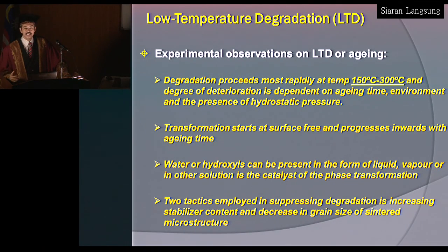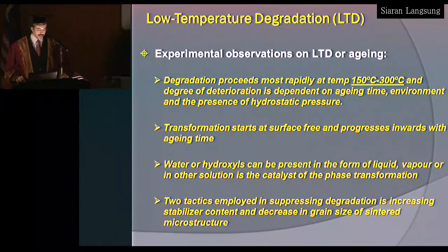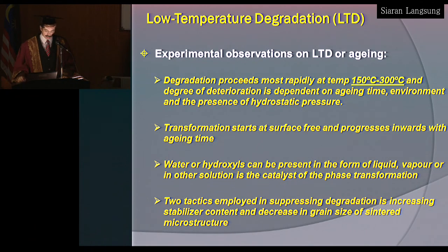So transformation toughening depends on the retention of tetragonal structure, and upon application of external stress, it transforms, and this creates a back stress and enhanced toughness. Okay, this material suffers from low temperature degradation. So what is low temperature degradation? Sometimes it is known as aging. Now, what has been found over the years is that degradation proceeds most rapidly at a certain temperature range between 150 degrees centigrade to 300 degrees centigrade.